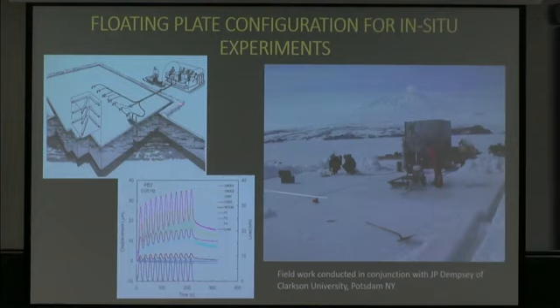It's like a compact tension experiment whereby you introduce a starter crack with a loading device and then some measurement gauges along the crack and then ahead of the crack in the region where the crack will go if it runs straight. My part of this, we will actually do some cyclic loading of the crack at stresses that are below the point at which the crack will propagate. So we can essentially query the whole sheet and get a snapshot of its constitutive response under a given set of conditions, which is something we're actually still working on analyses after quite some time here, but that'll be coming along.